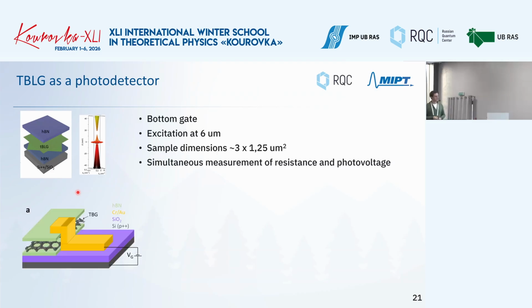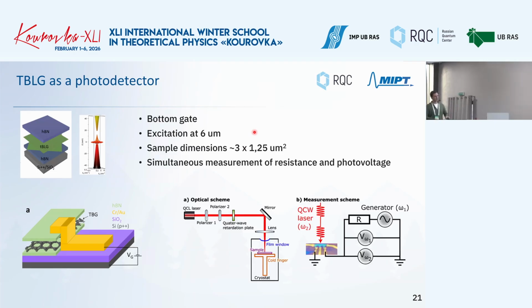We tried to study what happens if we shine light on this device, exciting it at 6 microns. And it turned out that the origin of the photodetection was quite different, and this is what we are studying in our work. The sample dimensions are really small, let's say 3 by 1.25 microns, and we excite externally with 6 microns. I will not bother you much with the experimental part. In order to detect, we use an optical cryostat. Everything is inside, we have the contacts and so on, and we shine through the cryostat and detect what is going on.